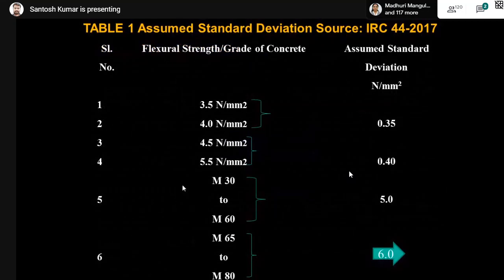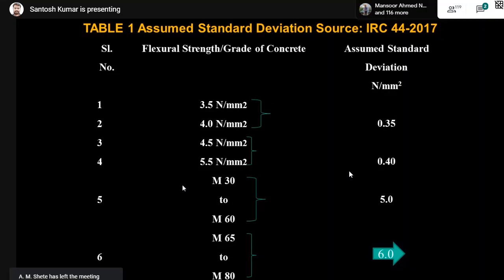So I don't want to focus more on it. And when it comes to this assumption of standard deviation based on flexural strength, if you want 4.5 to 5.5 Newton per mm square, the standard deviation shall be assumed as 0.4 Newton per mm square. When you design the concrete for a flexural strength of 3.5 or 4, the assumed standard deviation shall be 0.35 Newton per mm square. And as I told you, when it comes to high strength concretes above M65, the standard deviation, when you design from the compressive strength point of view, shall be taken as 6.0 Newton per mm square.